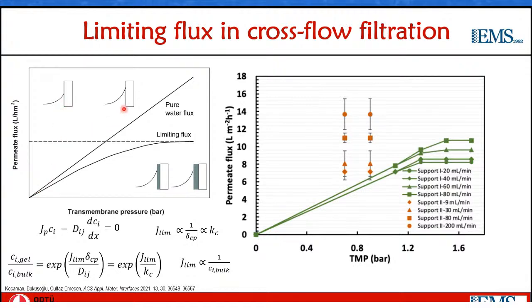As you increase the transmembrane pressure further, the concentration near the membrane wall further increases, but this can only happen until a certain concentration at the wall, which can be the solubility limit, the gel concentration, or the maximum packing density, depending on what material you're filtering. After this point, if you further increase the transmembrane pressure, because the concentration here cannot further increase, a gel or a cake layer starts forming. And as you further increase the transmembrane pressure, the flux does not increase anymore, but the thickness of the deposit increases.